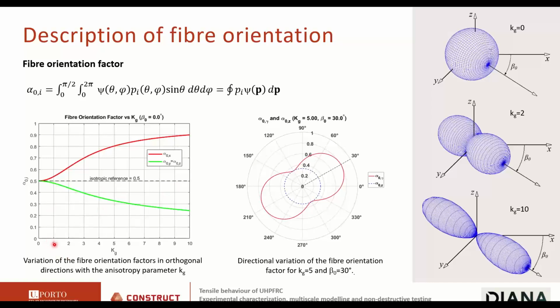Okay, we see that as we increase the parameter Kg, that leads to increased anisotropy in the fiber orientation distribution. We see that then the alpha values start growing in the direction along which the fibers are aligned, but this comes at a cost that the alpha value for the perpendicular directions decreases. Okay, so this explains the anisotropic response of the material when you have oriented fibers. So you will find more fibers in one direction, less fibers if the crack opens in the other direction.